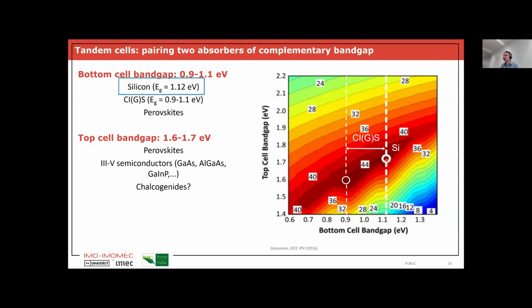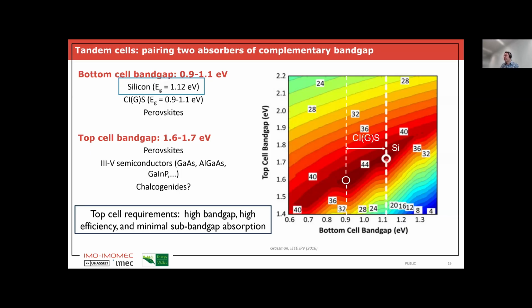And of course, you need to have a good top cell. And the top cell requirements are typically you need to have a high band gap, which to match with silicon should be around 1.6 to 1.7 eV. The top cell needs to be highly efficient and stable, etc., of course. And you should have minimal sub-band gap absorption. So it should allow the light that cannot be absorbed by the top cell to pass through and go to the bottom cell. And at the moment, the perovskite material, and I think already yesterday there was a talk about perovskite, so I will not go into detail there.